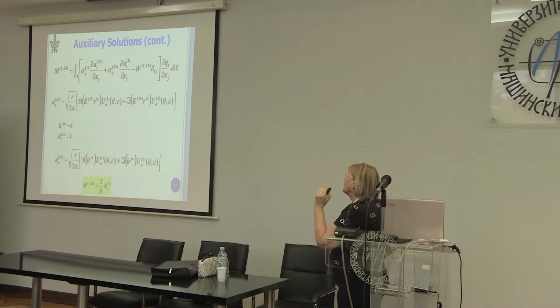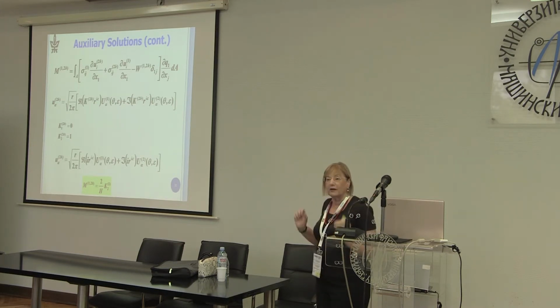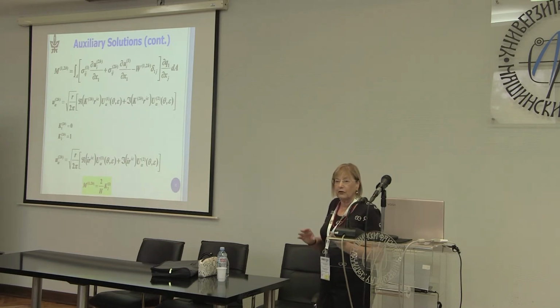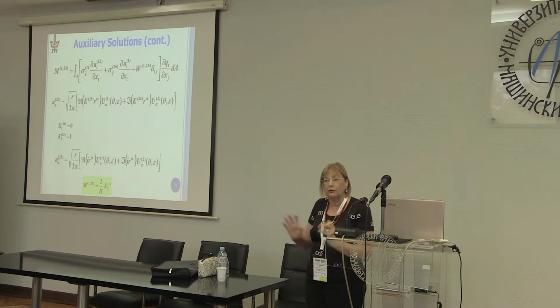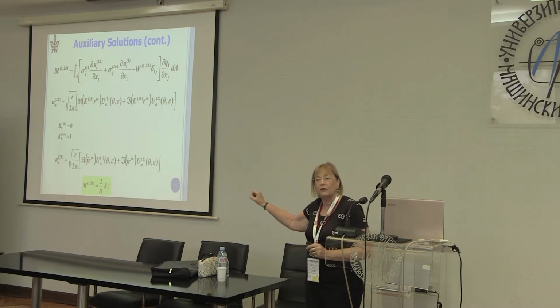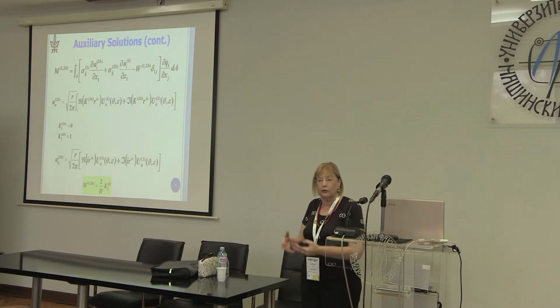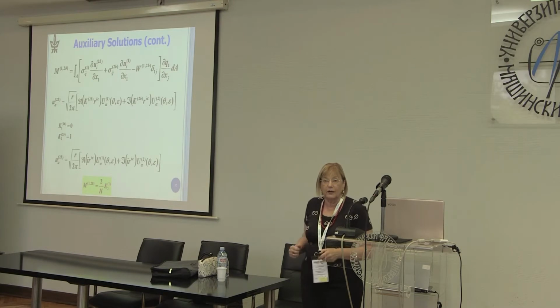All I want to give you as the message from this is that there are ways to get the stress intensity factors. The M integral is one way. There are other ways of doing it. You can do displacement extrapolation. You can do virtual crack closure technique. There are many other ways as well. This is just one way, and so I'm just telling you that if you want to calculate stress intensity factors, the literature is rich, and one of the ways of doing it is with the M integral.